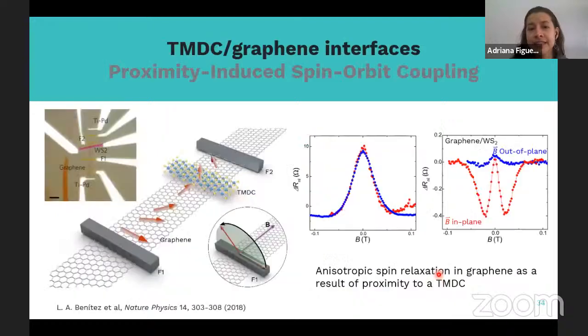And this has been studied in our group by colleagues, where they have studied proximity-induced spin-orbit coupling in graphene by investigating the spin relaxation and spin transport in these graphene-TMDC heterostructures. And they have observed that there is indeed an anisotropic spin relaxation in graphene as a result of that proximity to a TMD.